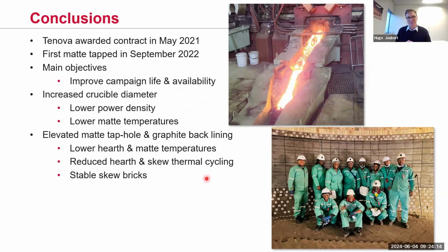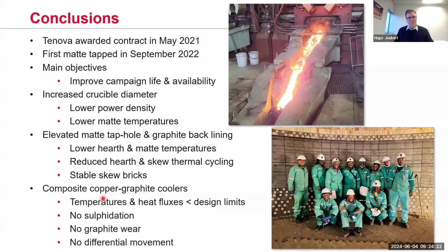But very importantly, it reduced the hearth and skew thermal cycling and resulted in much more stable skew bricks. And then finally, on the composite copper graphite coolers, the temperatures and heat fluxes are within the design limits. And to date, there's been no sign of sulfidation, graphite wear, or differential movements.